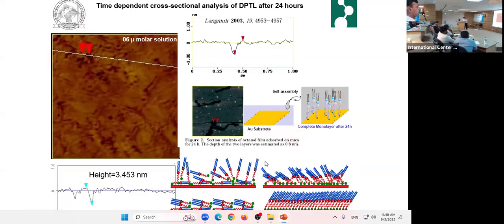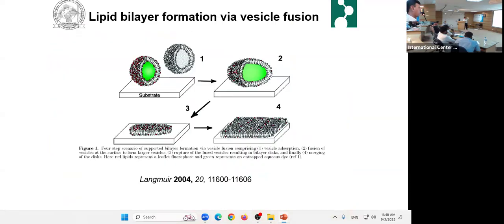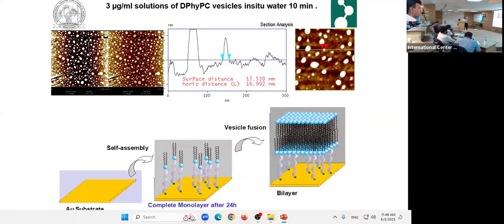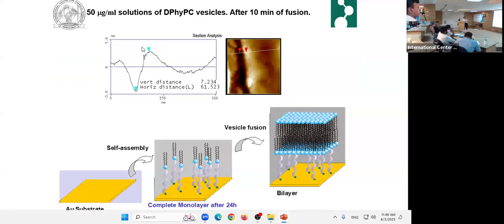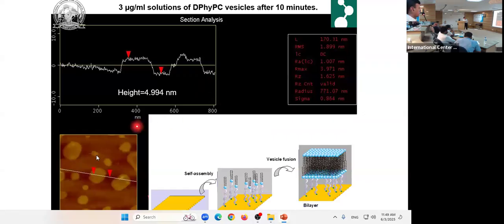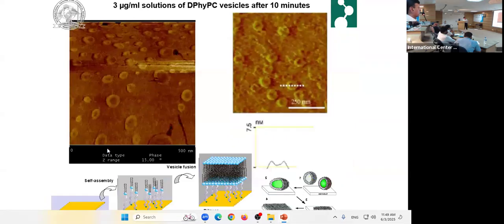Once we prepared this, we carried out the experiment, but we were not able to get the desired result. Then we put the vesicle on this surface and carried out the vesicle fusion, and analyzed the vesicles through atomic force microscopy. These are giant vesicles and small vesicles. The self-assembly of the vesicles was also observed. As you can see, the vesicles are collapsing. There are many vesicles, and these in the middle are hollow, very much matching this kind of vesicle.